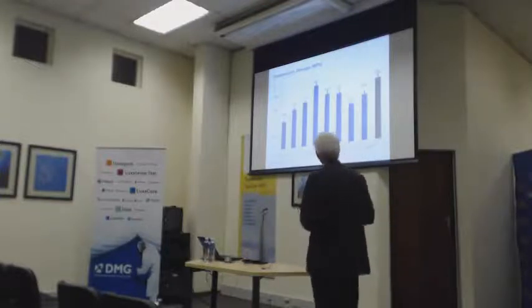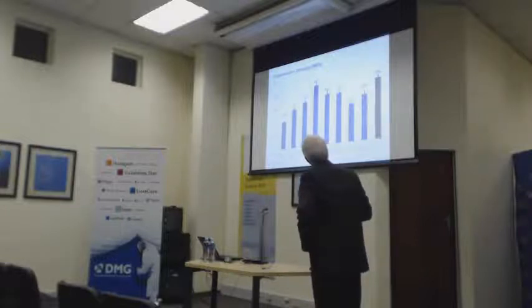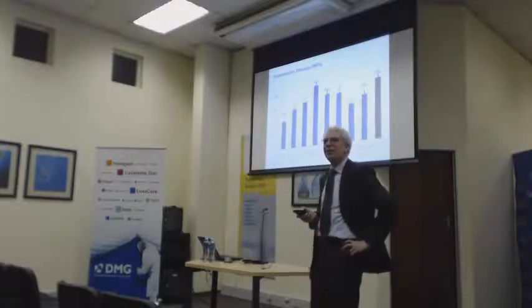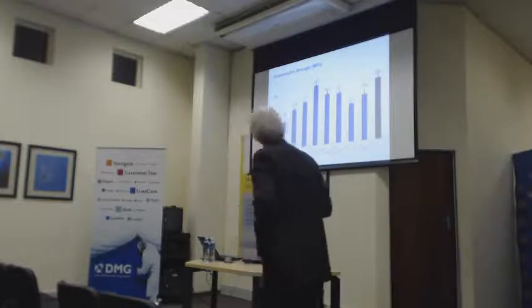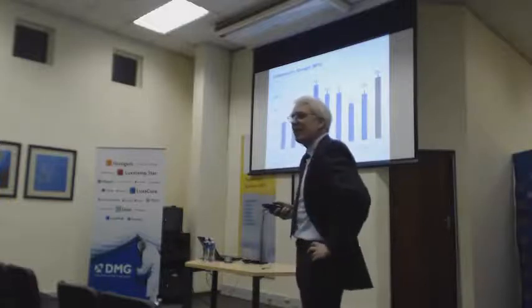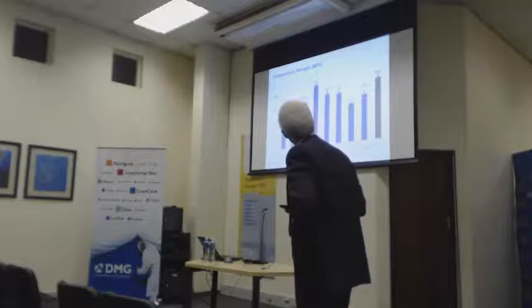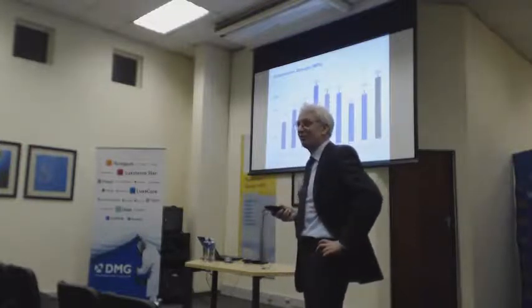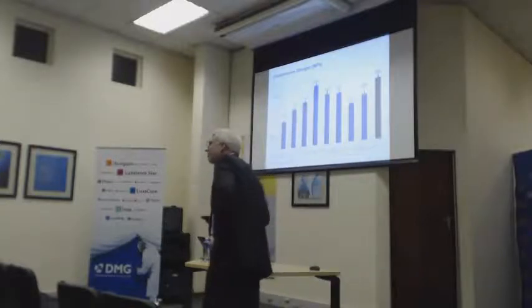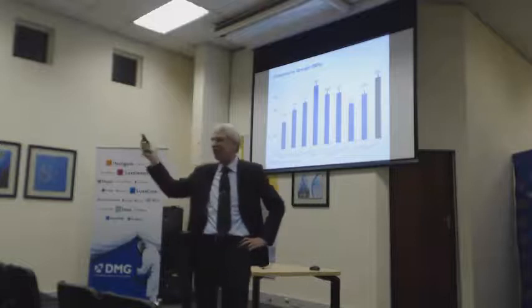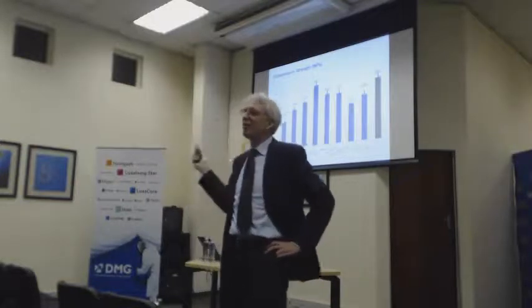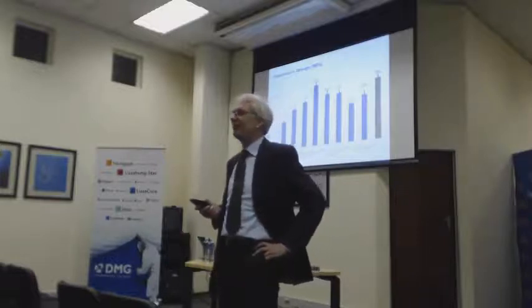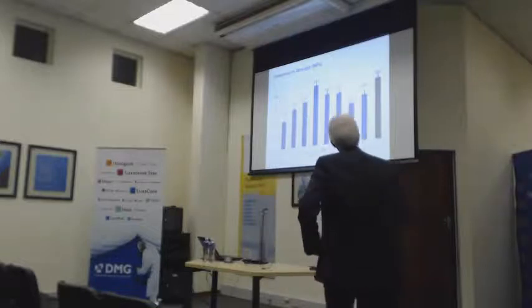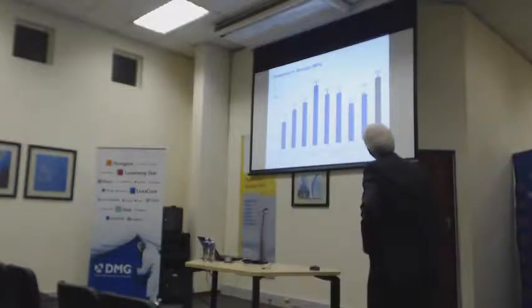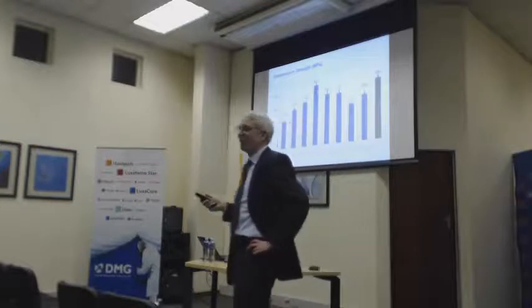So we have a 5-star rating for Luxacore, and in Germany we have a competitor here. This is Rebilda, probably not big here. Voco. It had 417 megapascals of compressive strength, and Luxacore only had 290. And that was statistically different. So the marketing department said, how can it be that we have the best core material as per Reality, and we have a compressive strength that sucks? So the R&D department was forced to do something about it, and they improved the compressive strength to 380, and that, believe it or not, is statistically identical to Rebilda. So they were happy about that.